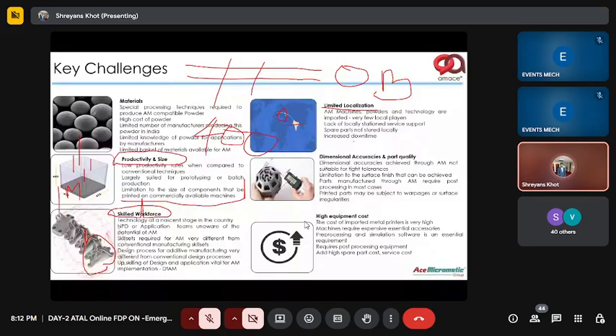Currently, because the laser spot diameter is limited to 80 microns and powder particles are limited to 20 to 100 microns, overall, with a 400 by 400 build, for dimensional qualification we can achieve plus or minus 100 microns as printing conditions. If we want to achieve tighter dimensional tolerances, we have to do machining.